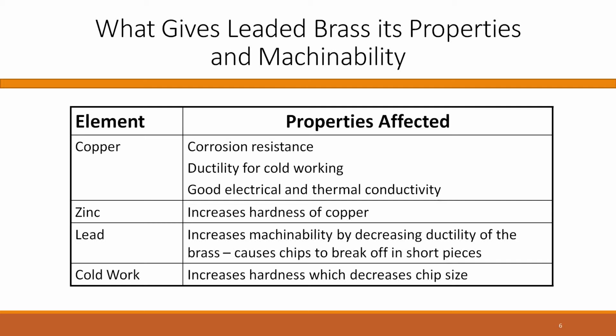And then you add lead to increase the machinability, and it's kind of a love-hate type of thing when you add lead, because while it decreases the ductility of the material so that you can get the best machinability, it also kind of fights against being able to roll really large threads into the surface of the rod. And consequently, you have alloys that might have less lead and more copper in them to make them more ductile, so you can get more cold formability out of them. Or if you're not concerned about that, then you can get less copper, therefore more zinc and more lead, and that combination gives you the best machinability possible.